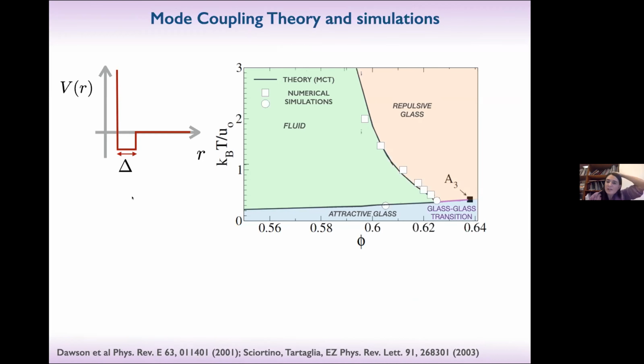And since I told you from the initial slide of Van Megen that MCT will predict the arrest transition in the wrong place of the phase diagram, what we did was both a mode coupling theory calculation and a numerical simulation of exactly the same model, a binary mixture of square wells, because otherwise it would crystallize. And then we mapped the simulations onto each other by extrapolating, for example, the relaxation time with the power law behavior, the simulation data, these data points, onto the prediction of MCT. The predictions of MCT were put forward for the square well model in this work.